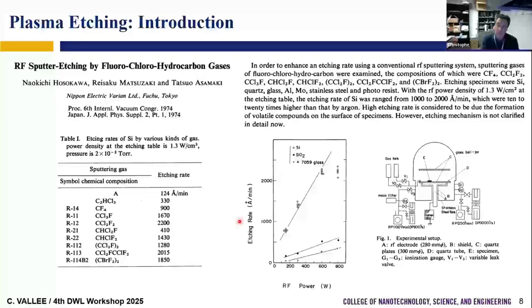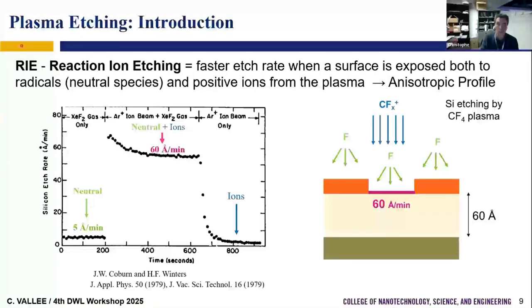What is very interesting is that in 1974, a Japanese group found that we can enhance the sputtering when we want to do the etching. Instead of sputtering with a rare gas, we can sputter with chemical ions, and then we can enhance the sputtering. This is the first paper where people observed that by using ionic assistance with a chemical, we may enhance the etching rate. This is the beginning of reactive ion etching. You can see a huge improvement of the etching rate compared to pure argon when you use chemical ions.